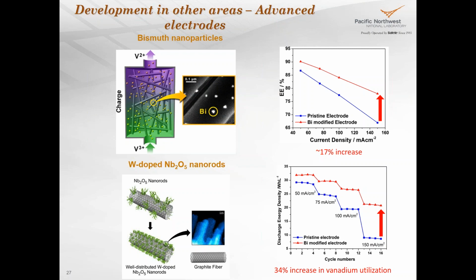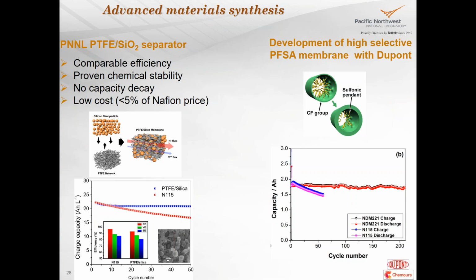We also have some effort on the material development on the membranes. So showing here is a PTFE silica separator. The PTFE and the silica both are very stable. They have high chemical stability in the vanadium electrolyte. Also, their cost is much lower than Nafion. I'm showing here the performance data there.